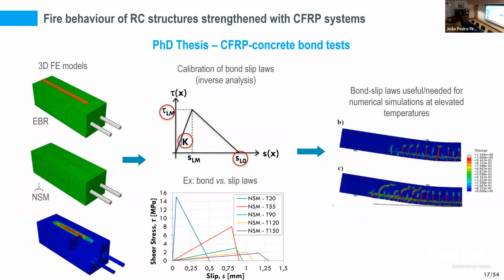And using all these new data at that time in the literature, we were able to calibrate bond slip models, also new to the literature. And these bond slip curves were very useful and important to be used in numerical simulation analysis of concrete members strengthened with these systems under fire.